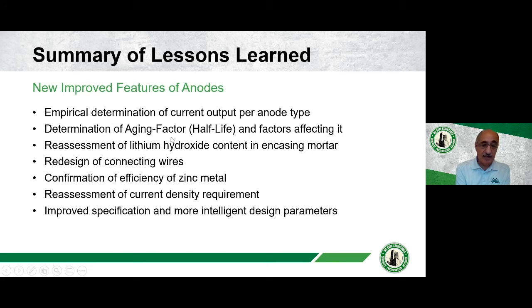We can determine an aging factor, which is related to the half-life principle. So every so many years, your aging factor could be 7 years, could be 10 years, could be 12 years. I'll show you later a table where we analyzed all of that. So we've now worked out how the current density diminishes with time. There was a reassessment, obviously, of the lithium hydroxide content, and like I said before, we've increased it in certain anodes up to 7 times as much lithium hydroxide.